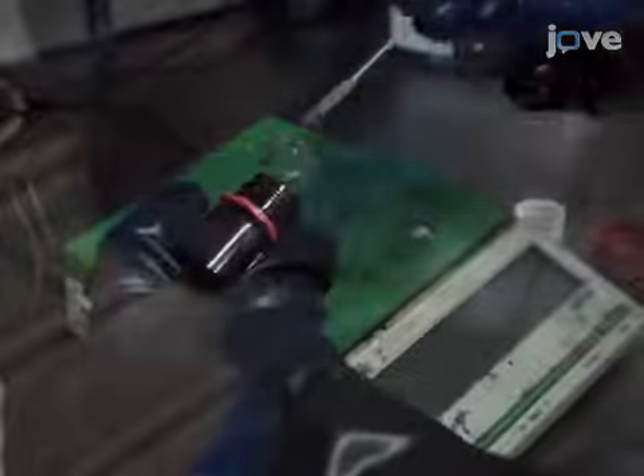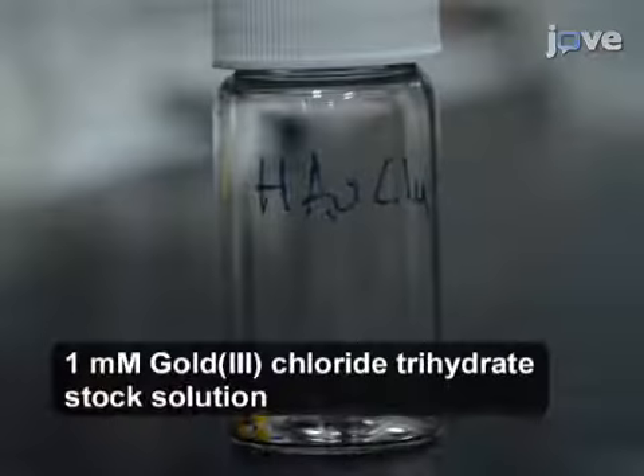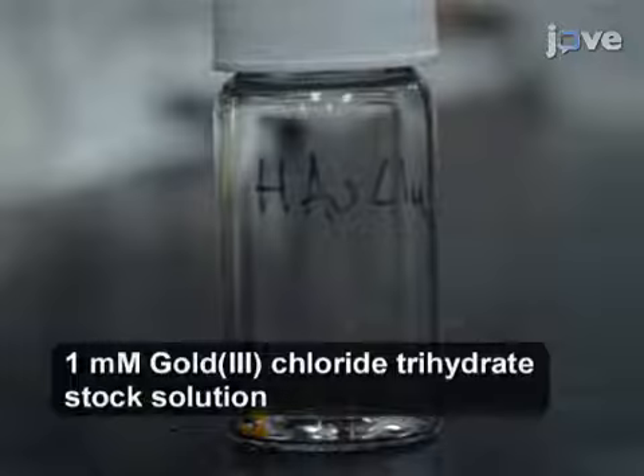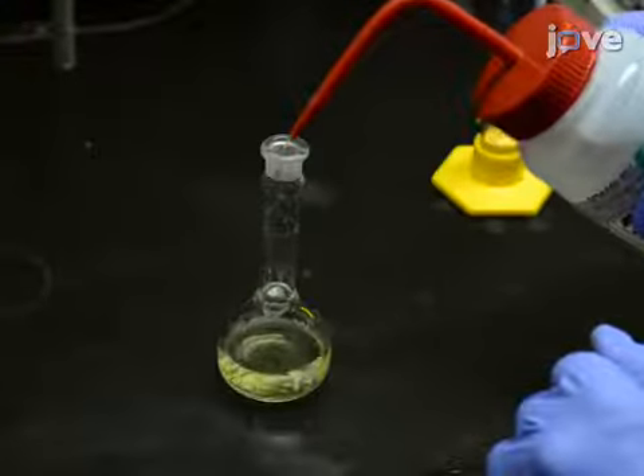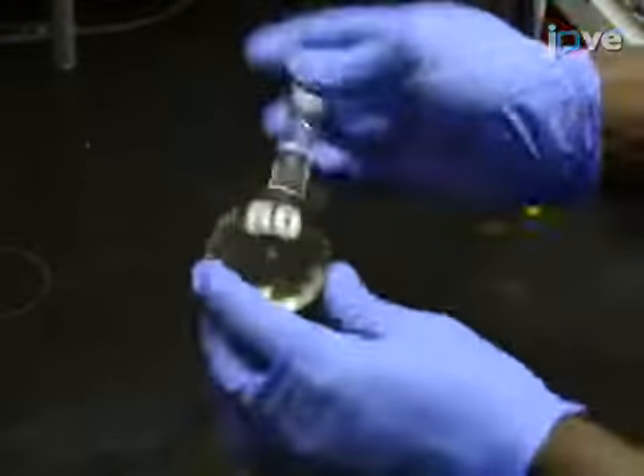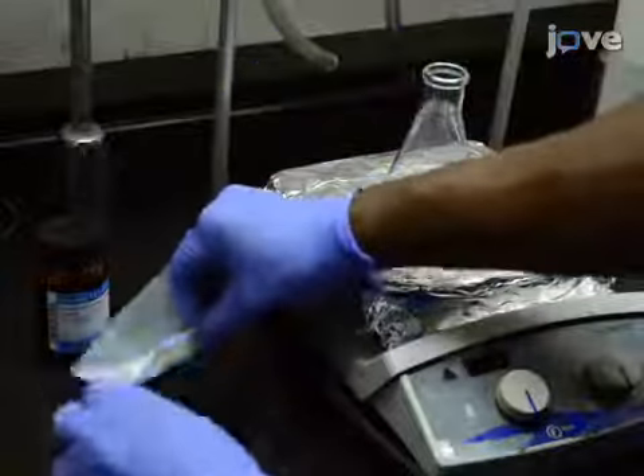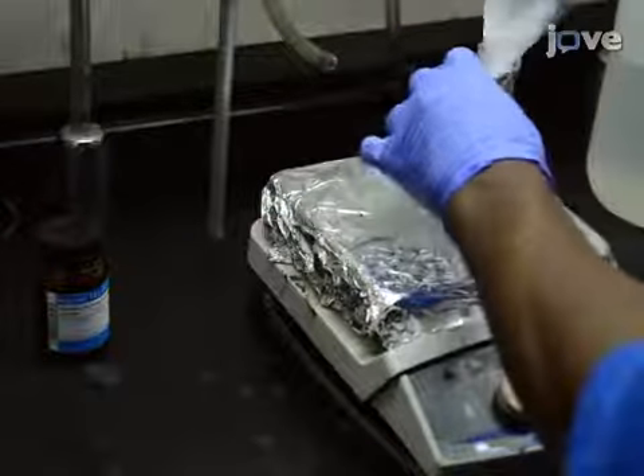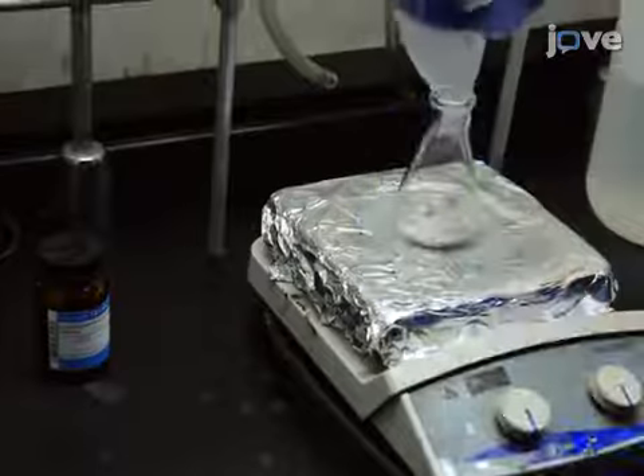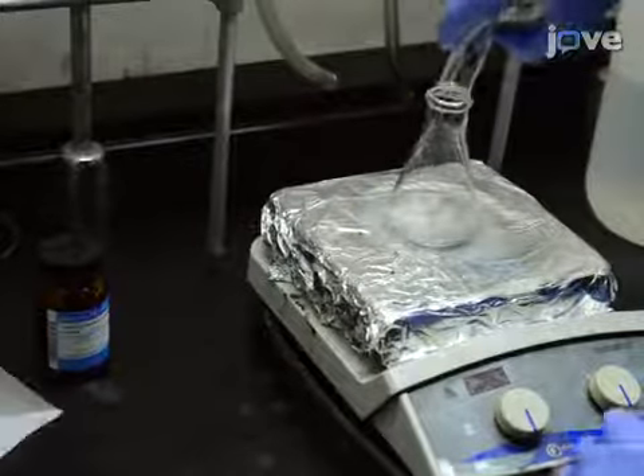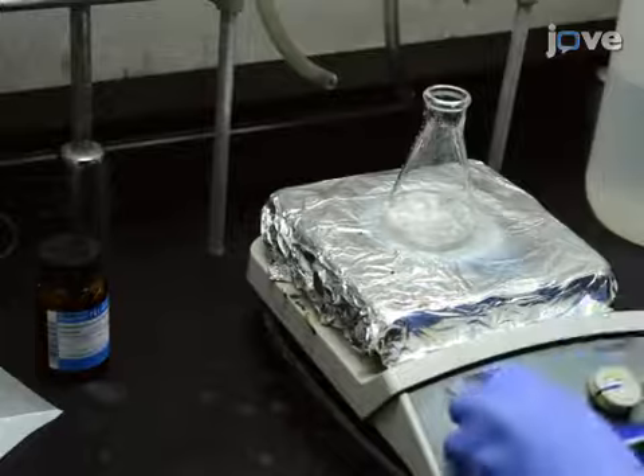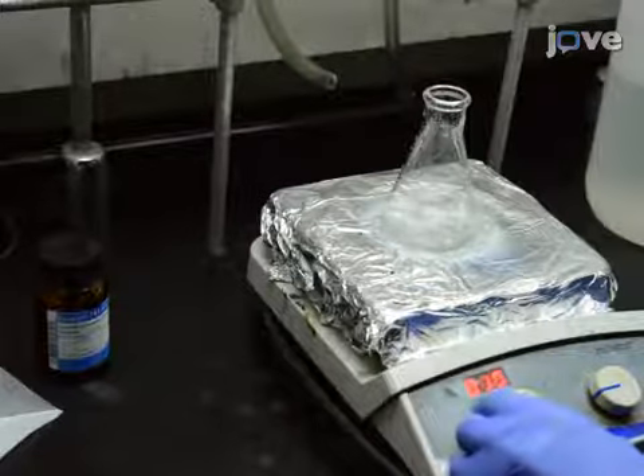To begin synthesis of gold nanoparticles, work in a glove box to weigh gold salt in a vial previously cleaned with aqua regia, before diluting with 100 milliliters of water in a volumetric flask. Then, add 3.2 grams of solid cetyl trimethylammonium chloride, or CTAC, and heat in 25 milliliters of water to approximately 60 degrees Celsius for dissolution.